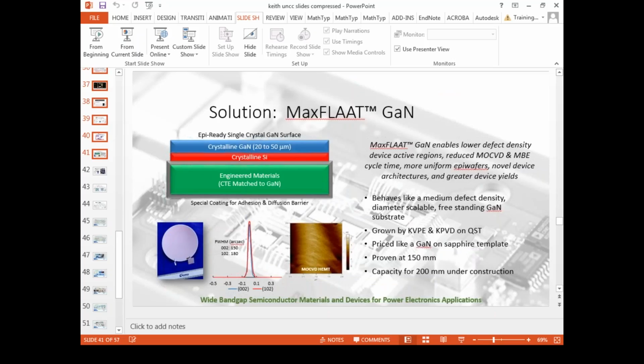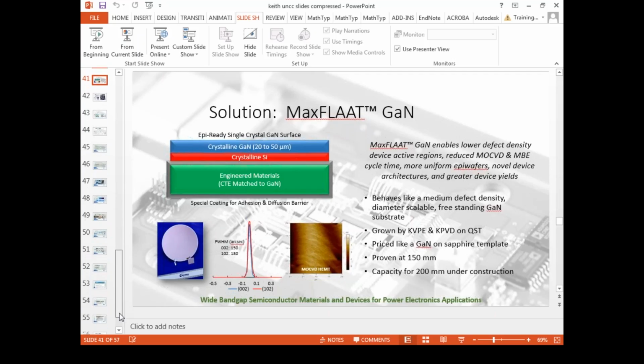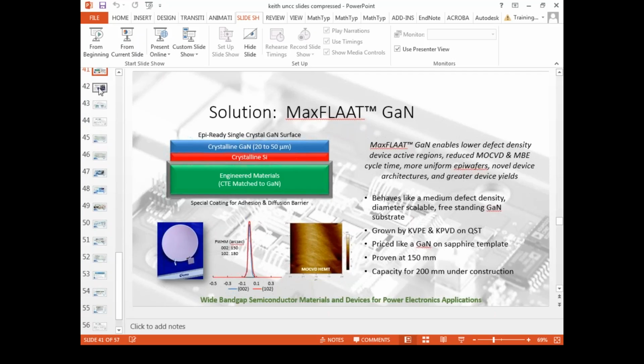So we've partnered with this group that came to us in May of 2015. They have a highly engineered material. They have special coatings on it. And then they put a smart cut thin layer of silicon on there using Navy technology. And these materials are picked to match the thermal expansion coefficient of gallium nitride. And they asked us, could you grow some GaN on there? And we grew maybe 30 microns pretty quickly.